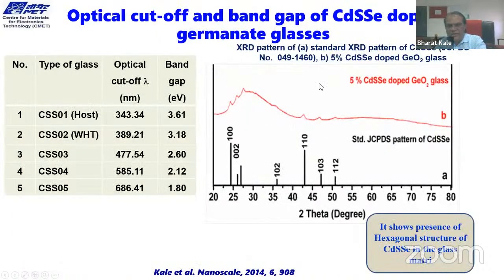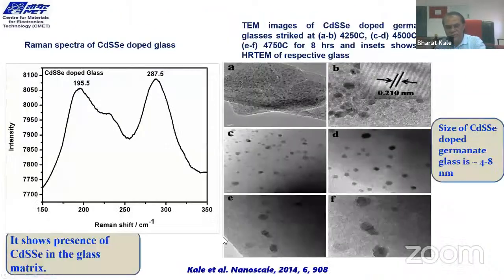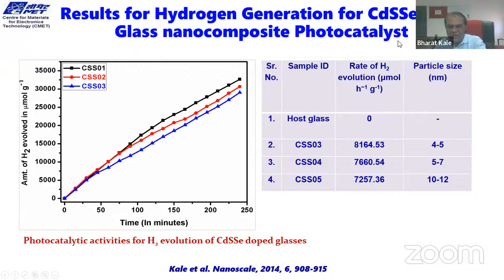Then Raman and XRD also show a very small amount of CdSe, and because of the very small amount, they are very weak peaks. And the band gap you see 3.6 to 1.80. We can tune. See, the CdSe quantum dot size is around 4 to 6 nanometers here again. And Raman clearly shows the formation of CdSe. And see here, generation of hydrogen is much higher as compared to CdS, because the band gap range is up to 1.7 electron volt.